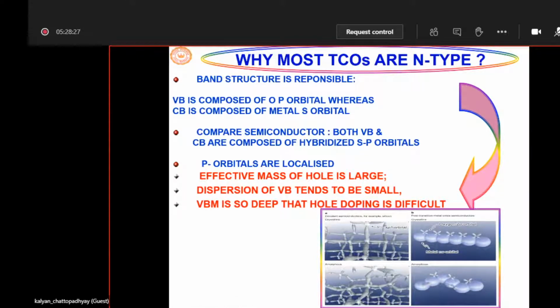But when you generate some holes somehow, for example by suitable doping, then the holes must be confined within this oxygen p orbital, because they are actually the constituent of the valence band. There you can find that the curvature is large and space is limited. In other words, you need a large electric field to move them. In physics we can say that it has a large effective mass. This is why in p-type oxide materials, achievement of higher mobility is extremely difficult. Also, the valence band maxima is so deep that it is difficult to get a shallow acceptor level. So these are the reasons why, so far, an efficient p-type TCO is not achieved.